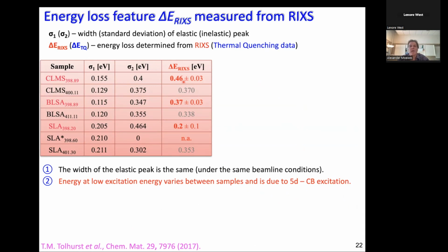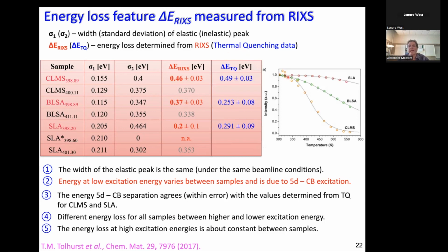Now, what we do is we compare these values with the quenching data. Quenching, here again, we show the thermal quenching. This was due to promotion of 5D electrons through thermal excitation to the conduction band, and therefore reduction in luminescence. So these values with an error bar, and they, of course, of lesser quality or relatively poor statistics, agree, which led us to assign these loss features to indeed the energy loss feature is due to the promotion of a europium 5D electron to the conduction band. So this is exactly what I promised originally. So with this technique, we found a way of determining the position of the 5D orbital with respect to the conduction band.